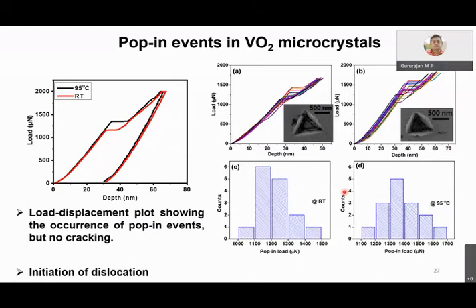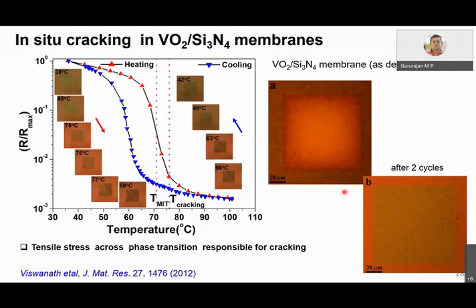Vishnu, I also had a question about the transformation itself. Is it some kind of martensite-like transformation or massive transformation? Yes, as far as I understand, initially there was no clarity. For example, for zirconia, people would say it is a martensite, although it happens at much higher temperature. For VO2, there was no strong statement, but recently there are many papers. Some of the kinetic studies, the rate dependence and so on, also seem to indicate it is a martensite phase transformation. There are a few papers that also established the twin boundary across the phase transformation as well.